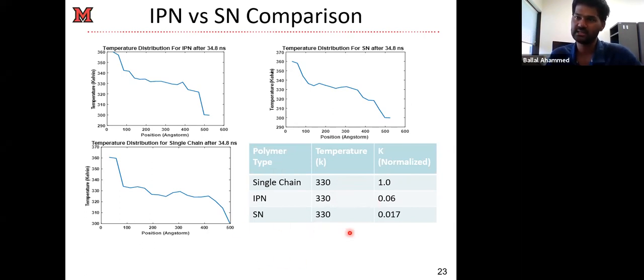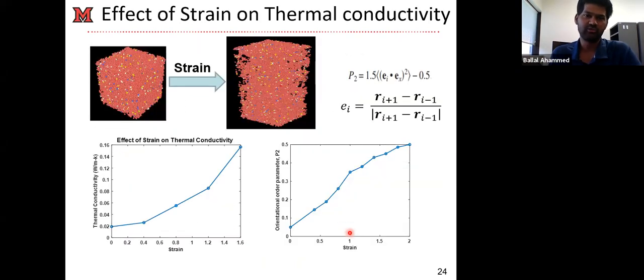For the SN case, there is less bond formation, and also the structure is more irregular in comparison to the IPN. That leads to more phonon scattering, which reduces the thermal conductivity. Then we tried to find some way to increase the thermal conductivity of these polymeric materials. Because for some applications, we need quick heat removal from polymer-based composites, or in some other applications, we want the polymer to be very conductive.